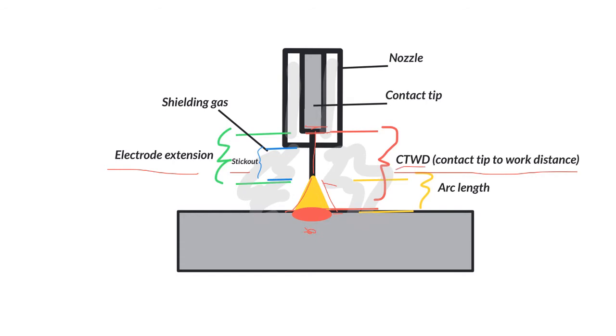I'm just going to throw out a random short circuit setting. Maybe we're around 18 volts and let's say 200 inches per minute. I would say the distance between the nozzle and the base metal is maybe 3/8 to about a half inch off the base metal. Okay, so it's not a huge gap. There's not a whole lot of room there, but it's also not too close where you can't really see the wire. You want to be able to see the wire so you can see the arc, the puddle, and everything else going on there.